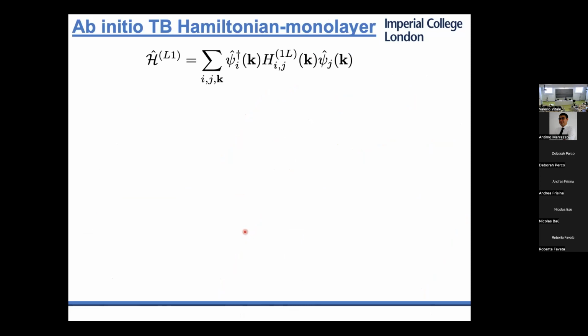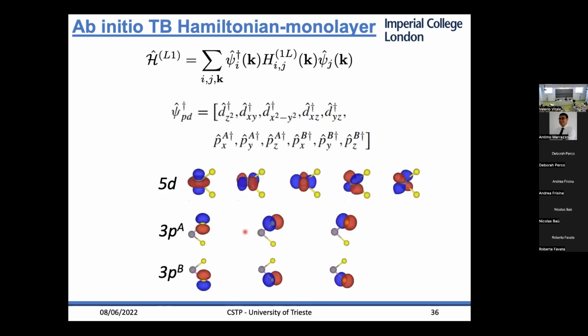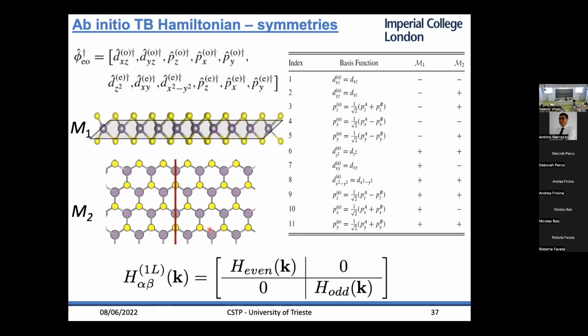Right. So this is a way to compute the structure at the classical force field level, but as I said, they are quite accurate in the regime that we're interested in. And then what we did was to construct a tight binding Hamiltonian, which we call ab initio, and I will explain why, from basically using the information only on unit cells. So the idea is to start from a basis of 11 orbitals or Wannier functions. These are the 5 d orbitals on the transition metals and the 3 p orbitals on the chalcogens. And then we exploit some of the symmetries of the system.